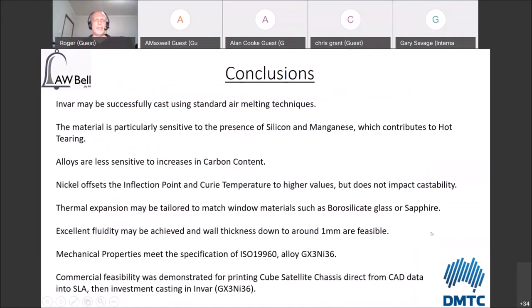So in conclusion, Invar may be successfully cast using standard air melting techniques. The material is particularly sensitive to the presence of silicon and manganese, which contributes to hot tearing. The alloys are surprisingly less sensitive to increases in carbon content. We found that nickel offsets the inflection point and Curie temperature to higher values, but does not necessarily impact the castability. The thermal expansion may be tailored to match window materials such as borosilicate glass or sapphire. Although we haven't been asked to do that at this stage, we did find that to be feasible.